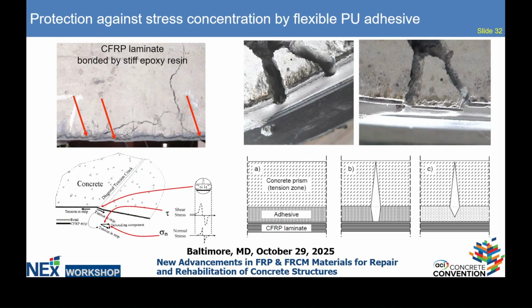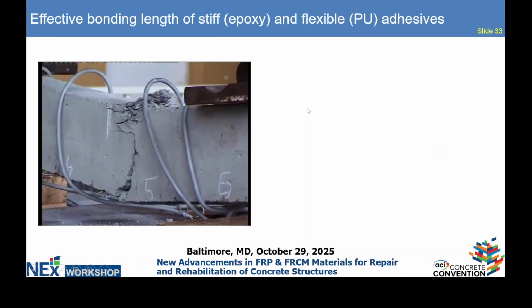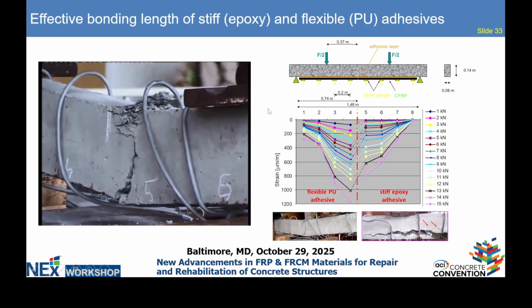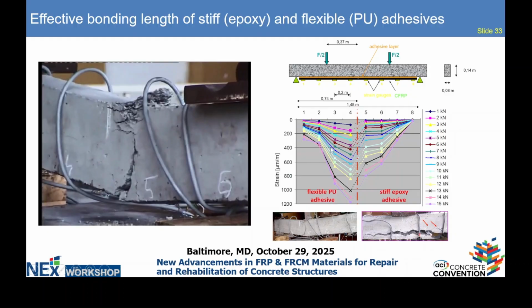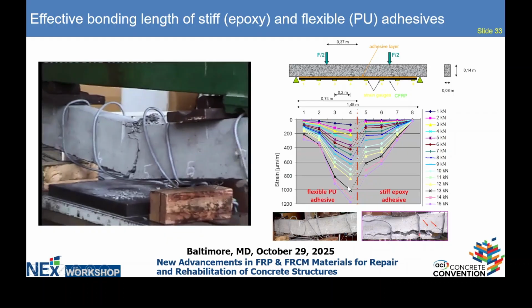So when we have stress concentration according to shear, as Cristiano presented, in stiff epoxy we have direct attack of the crack on the composite material. When we have flexible material, the composite is protected because the stress is more evenly redistributed. So when we compare two systems, on the right-hand side stiff epoxy, on the left-hand side flexible adhesive, you can see that for the same load, we have more effective use of the composite material according to these strains measured on the surface. So also, the damage is not sudden.